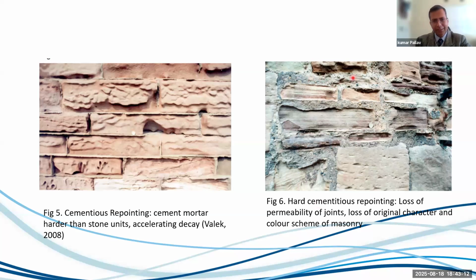So in this case, if you see, restoration was done, and what they have done is they have used quite a strong, hard cementitious material for the pointing and repointing of this. So both ways, if you treat with a stronger thing, then your material inside is weaker, it will deteriorate, right?